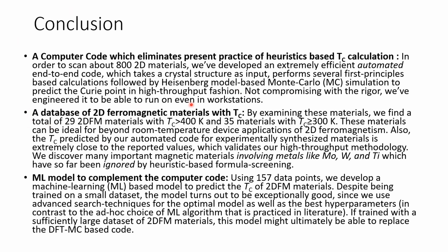The second part of the results is the database, a sub database rather, of 2D ferromagnetic materials with TC. By examining all of these materials, we found a total of 29 2DFM materials with TC greater than 400K, that is about 127 degrees centigrade, and 35 materials with TC greater than or equal to 300K, that is room temperature. So these materials show promise to be used in real life devices where the temperature can go pretty high, but these materials would still retain their ferromagnetic property, and so you can use them in various devices.